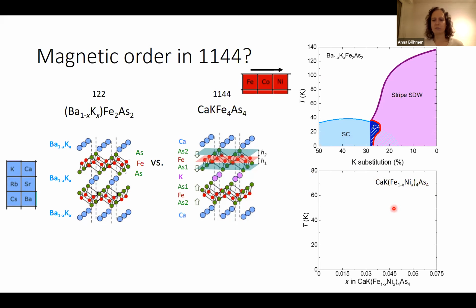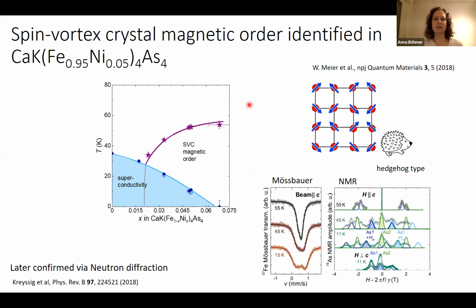The phase diagram we found upon nickel substitution indeed shows some magnetic order. What we find is the suppression of superconductivity. One might think half a superconducting dome, maybe, and we find a magnetic phase coming up here. This magnetic phase was identified to be not the stripe type order as what comes to our mind when we think of iron-based materials, but no, it's what's called spin vortex crystal magnetic order. That was also mentioned yesterday.